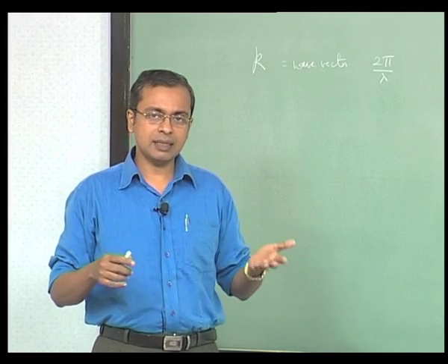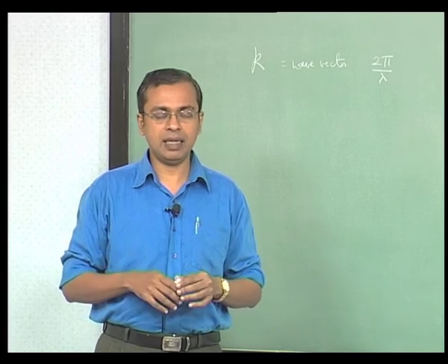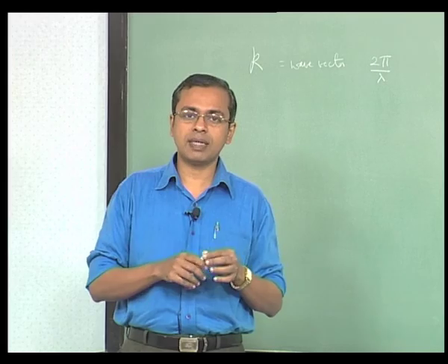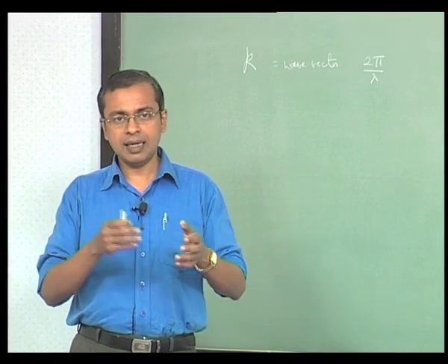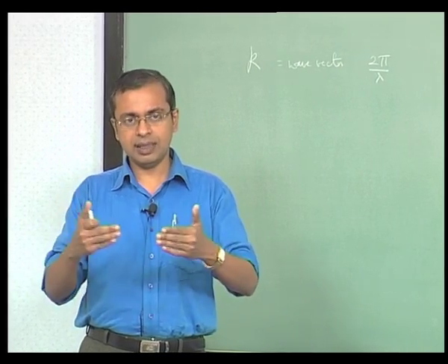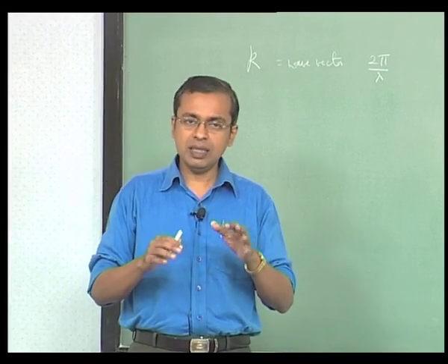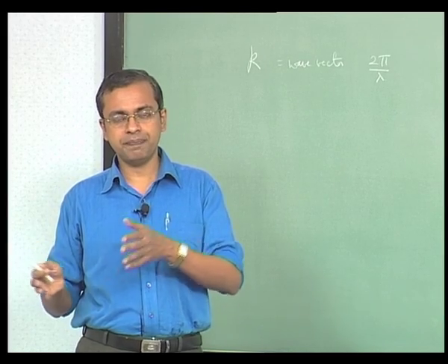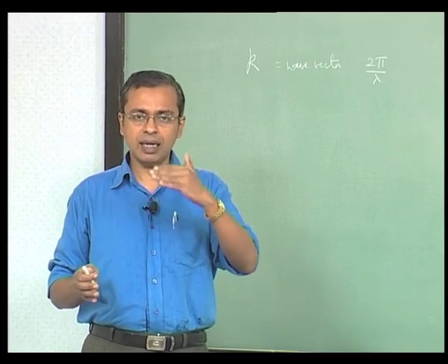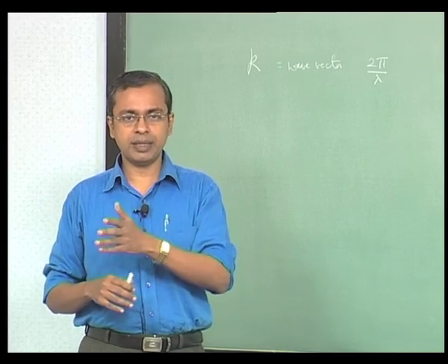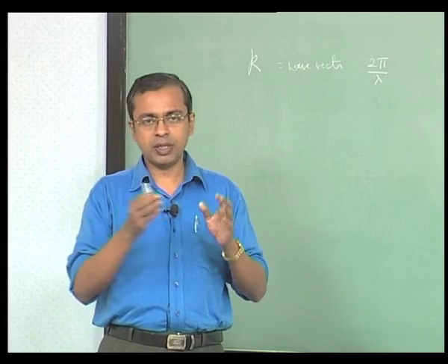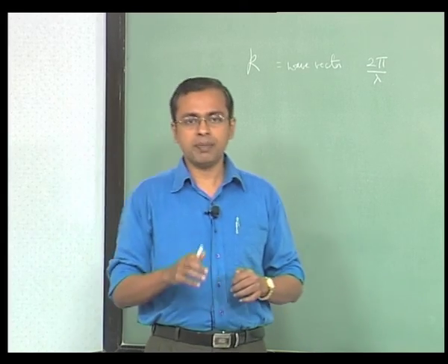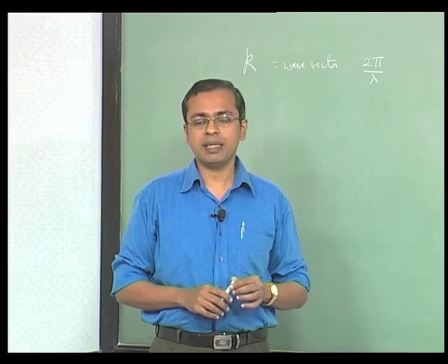Of course, last class we looked at reciprocal lattice as an independent entity. We just basically said that given a real lattice which has unit vectors a1, a2 and a3, we can specifically create a reciprocal lattice which corresponds to this real lattice, with the definition of the reciprocal lattice vectors, unit vectors in the reciprocal space b1, b2 and b3 having specific relationships to a1, a2 and a3. Okay. So we had a cross product: b1 was a2 cross a3 by the volume of that unit cell, and similarly b2 and b3 were described.